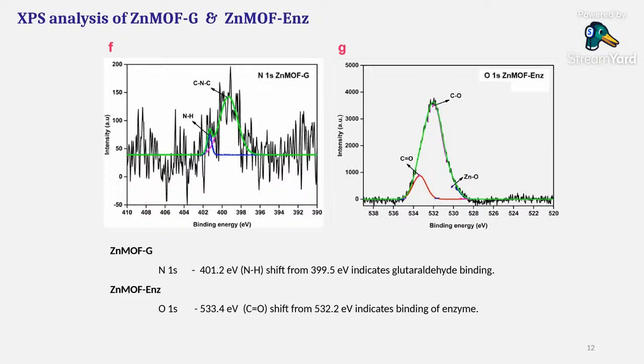Here you can see the zinc MOF N1s at around 401 electron volt, a shift from 399.5 electron volt, for the glutaraldehyde binding. Once the enzyme is coated, the oxygen shifts binding energy: from 532 electron volt, it moves to 533.4 electron volt.